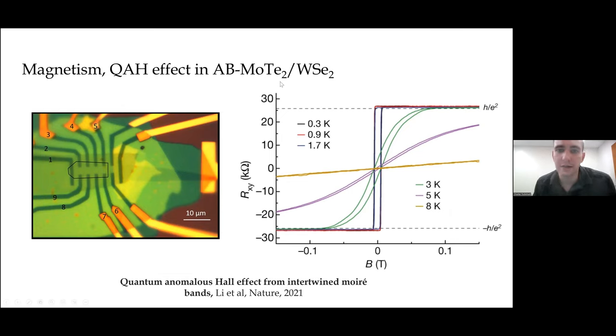So the next thing I'm going to talk about is a different system. This is AB-aligned molybdenum telluride tungsten selenide. It is also an exfoliated heterostructure. What I'm showing at right is the anomalous Hall resistance as a function of magnetic field. So you can see that we have quantization of the anomalous Hall resistance. This is also a Chern 1 system. And we have a small magnetic hysteresis loop. And this is from Kin Fai Mak and Jie Shan's group.